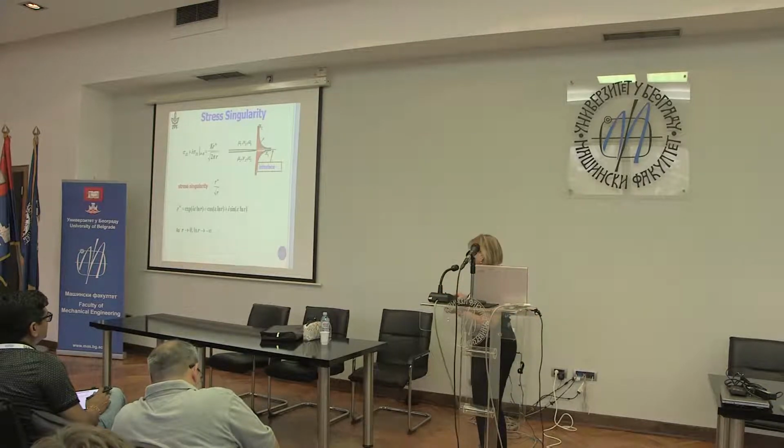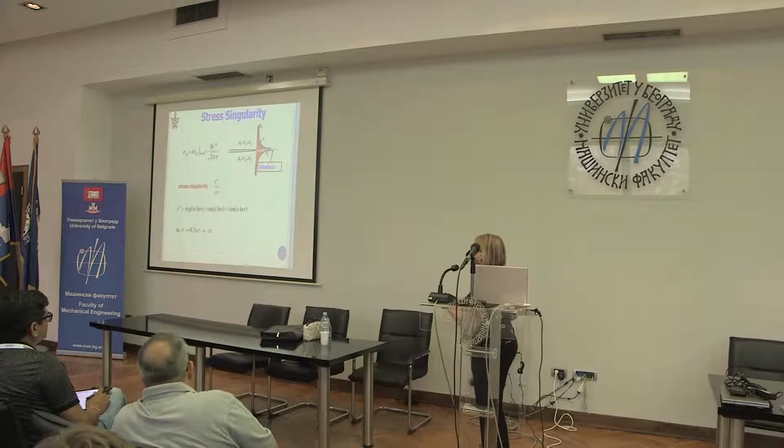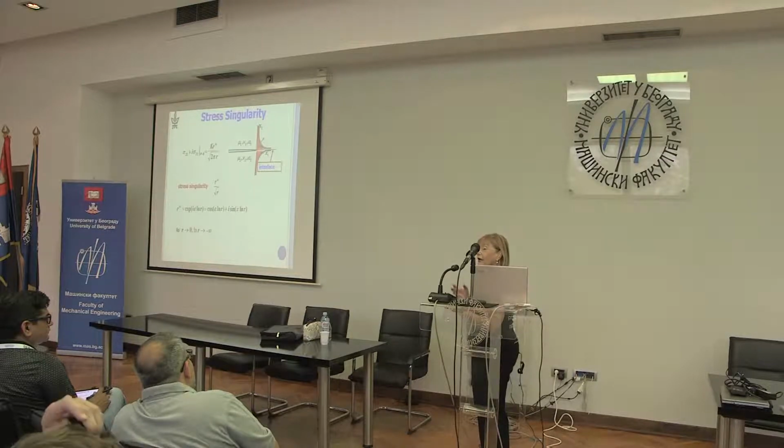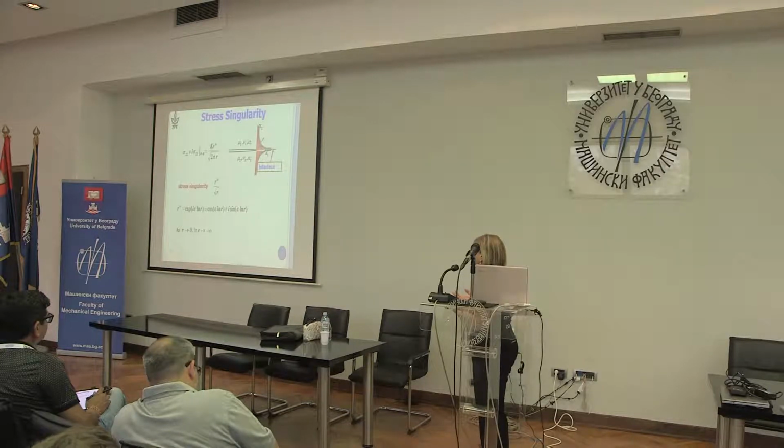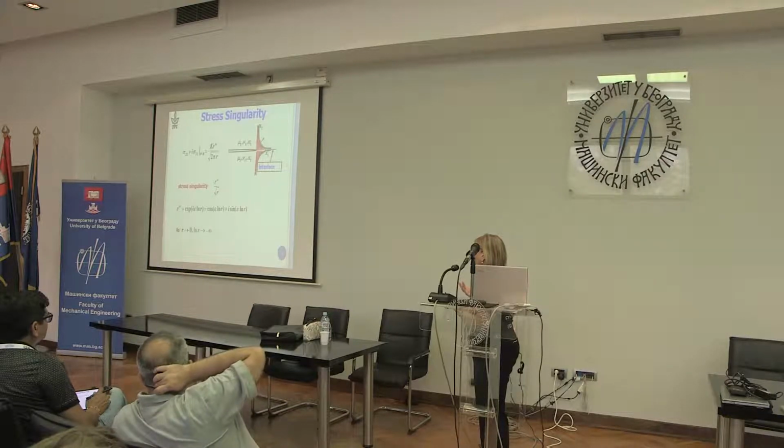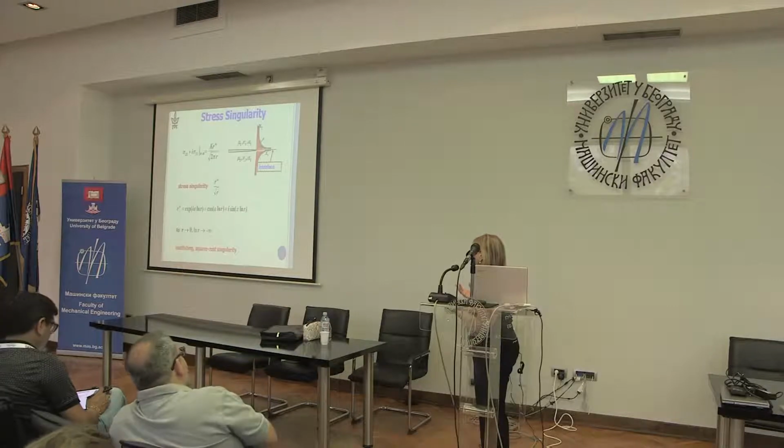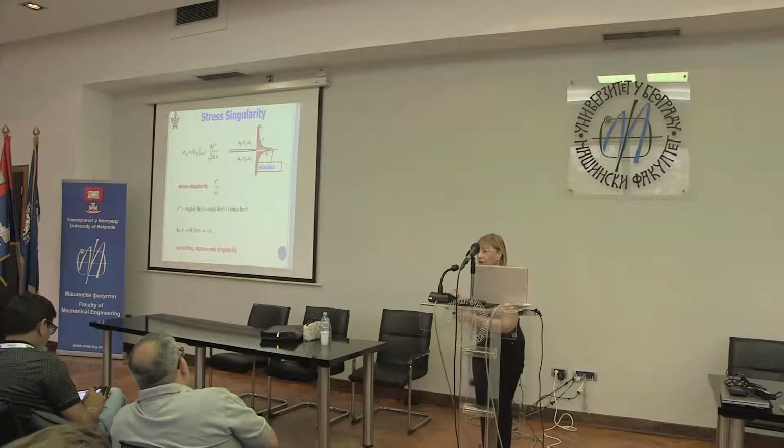We're going to look at the crack face displacements, and they also oscillate, but when they oscillate, they interpenetrate. The upper crack face goes mathematically into the lower crack face and vice versa. Of course, that's not physically tenable, and so if you want to do something physical, you have to assume that you have contact here. That's physically what would happen. But anyway, we can live with it, and so we say that we have an oscillating square root singularity.